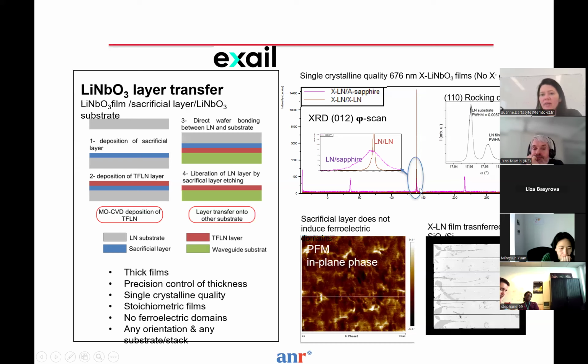If I grow on sapphire, this is for X-cut lithium niobate, which is interesting for photonics. We grew the films without cracks or any problems at 680 nanometer thickness. And we see that we don't have two orientations in the plane. When we grow on sapphire, we have X plus and X minus growing together. On lithium niobate substrates, which have just a single orientation, if the substrate is X plus, it grows X plus; if it's X minus, it will be X minus. And the rocking curve is very close to the substrate, so it's the resolution of the diffractometer, and the rocking curve is 0.092.